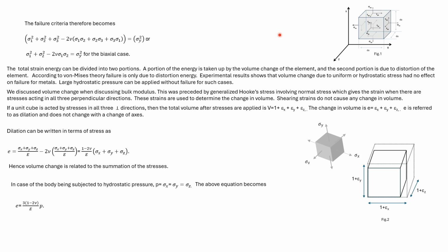As per von Mises' theory, it is the distortion portion of the energy that is responsible for failure. Experimental results show that hydrostatic pressure has no effect on the failure of metals. We earlier saw that Tresca's failure criteria is aligned with this fact. A change in hydrostatic pressure does not affect Tresca's failure criteria. Now, hydrostatic pressure causes only volume change. So von Mises' theory is also aligned with the fact that hydrostatic pressure will not affect failure.